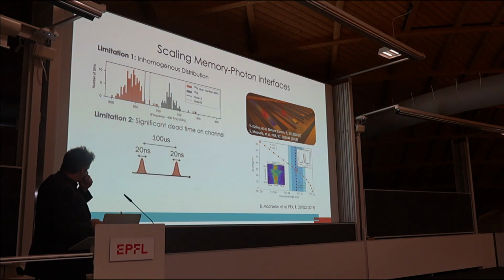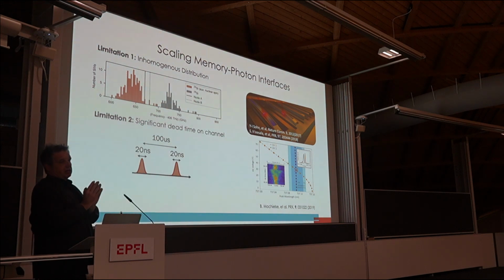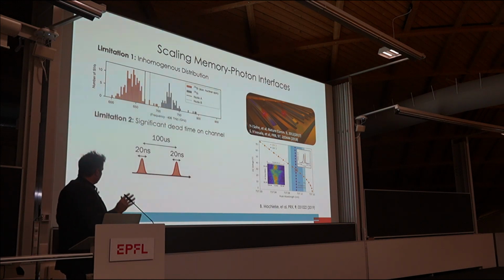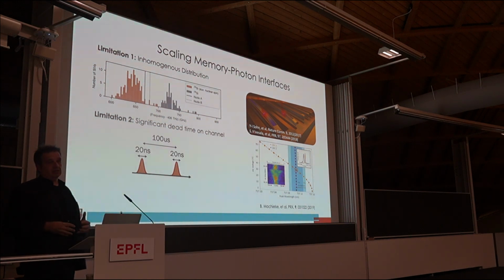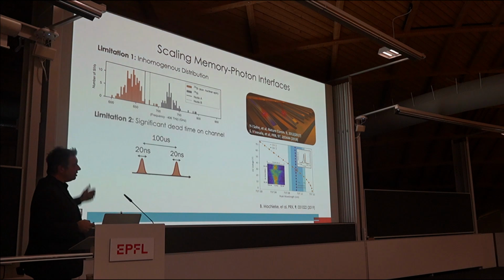Another problem is that photons emitted by silicon vacancy color centers are slow. They're long, on the order of 20 nanoseconds. And also, we use so-called timing qubit encoding of quantum information in these quantum protocols. And the length of the timing qubit, given by how long it takes to prepare the silicon vacancy in a particular state, is on the order of 100 microseconds. So your communication rate, if this is the case, can never be bigger than 10 kilohertz. Right now it's probably a few hertz. So that's a problem because it's always going to be slow. So we need to address that as well.